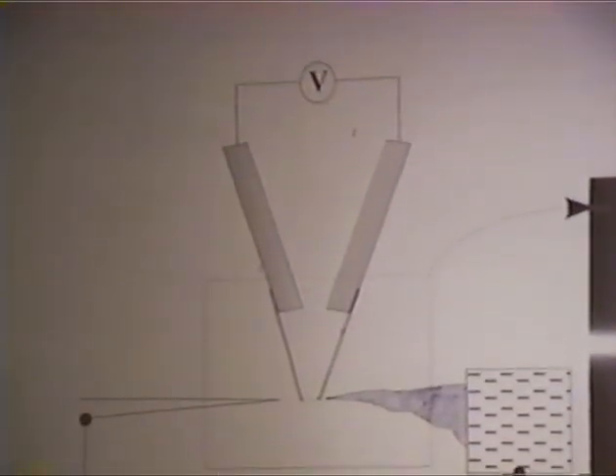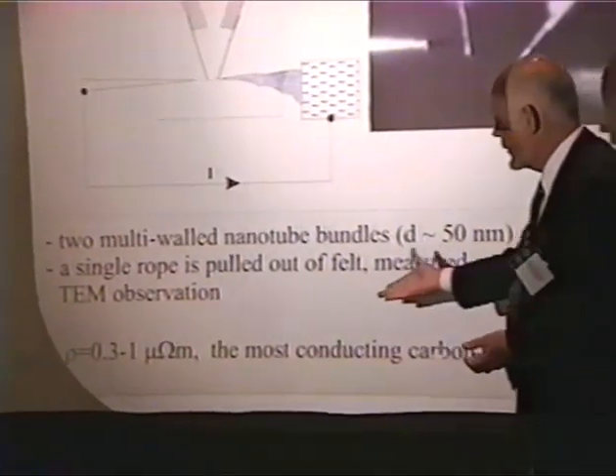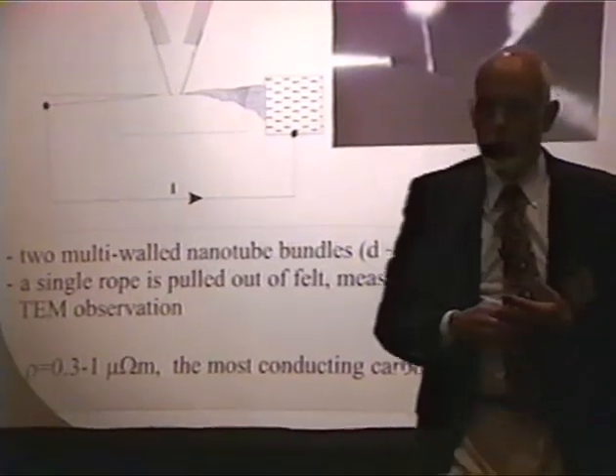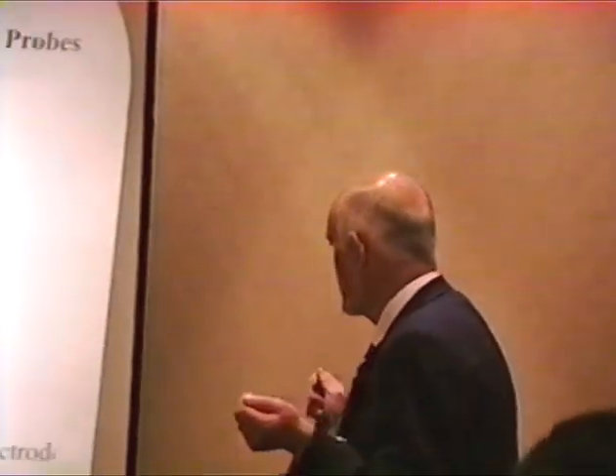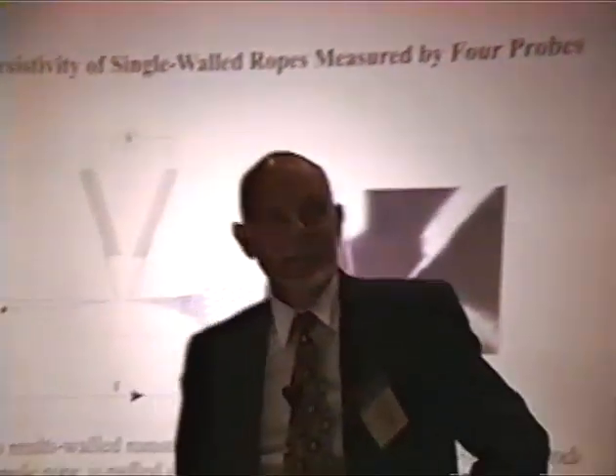Well, really, actually, it's an upper limit of the resistivity. And it turns out that it's a little bit better than perfect in-plane graphite for this particular rope. Actually, we used this scheme in the groundbreaking ceremony of the new nano building at Rice. It was a sort of a ribbon cutting ceremony, except in this case, it was a nano ribbon. It was the first nano ribbon cutting ceremony anybody had attended where they couldn't actually quite see the ribbon they